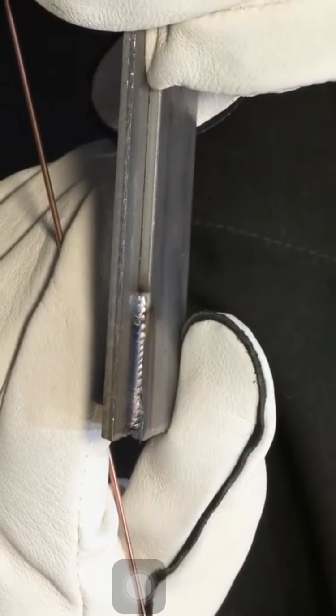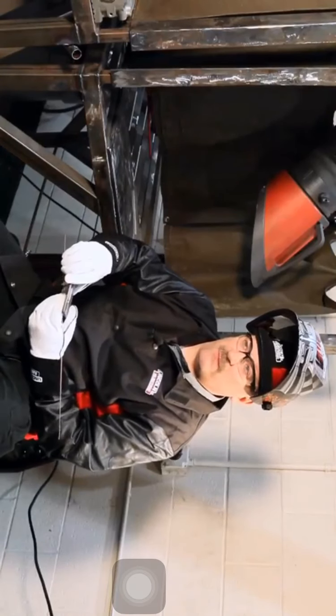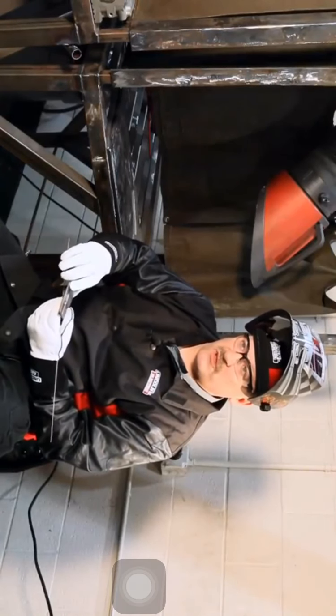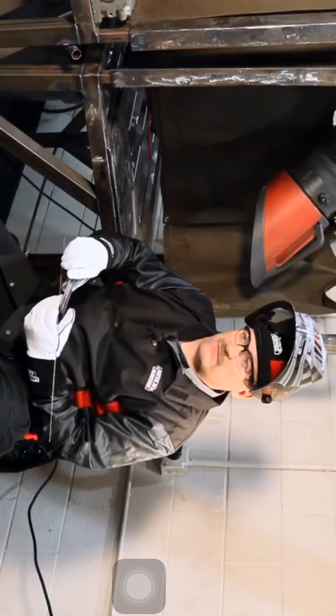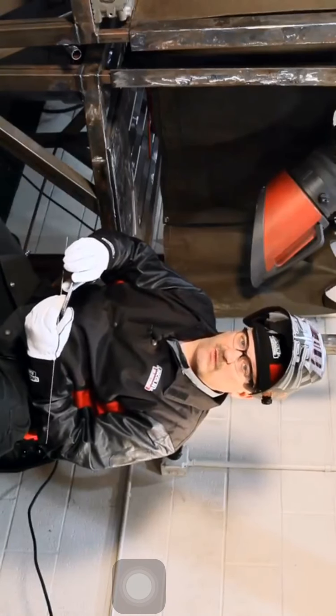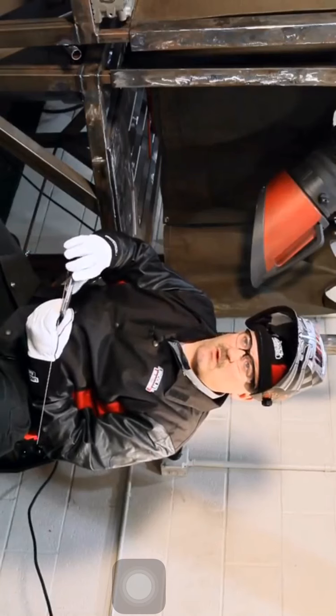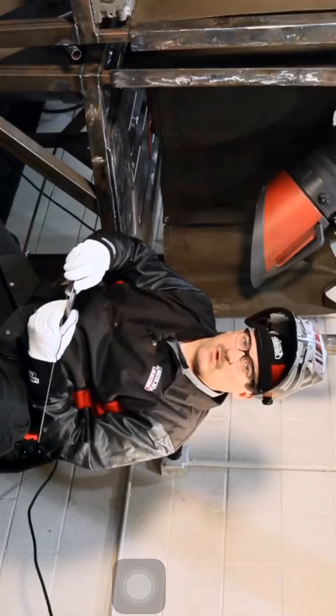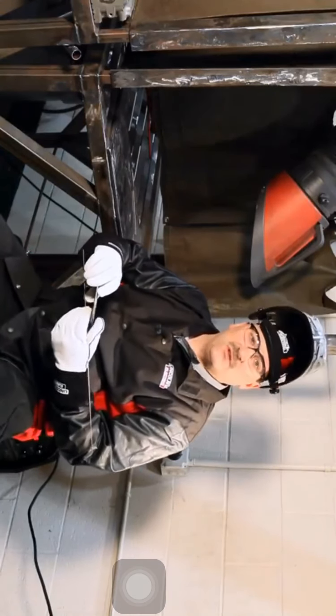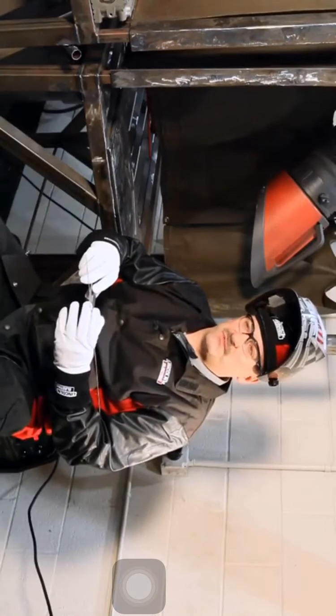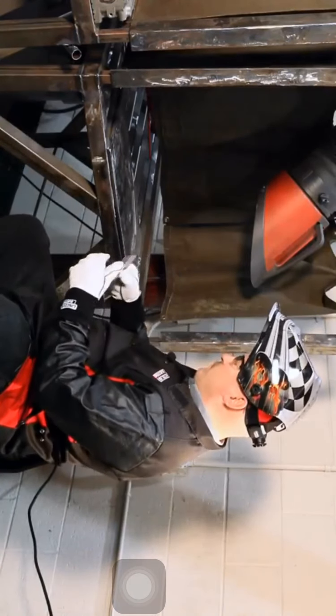I started a small TIG weld here, and I used a 1/16 filler. This material is a little bit under 1/8 of an inch thick, and I made sure that the top toe of my weld didn't go up to the top of that plate. I went about 3/4 of the way up, so my leg size is about 3/4 the thickness of my material. Usually that's adequate for a full strength weld on a fillet weld. So we're going to shoot for that. Over welding would only cause more heat input and more distortion, and that's one of the big problems with welding sheet metal sometimes. So I'm going to turn this piece over.